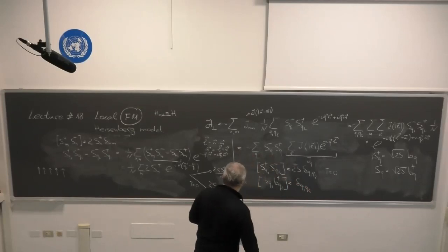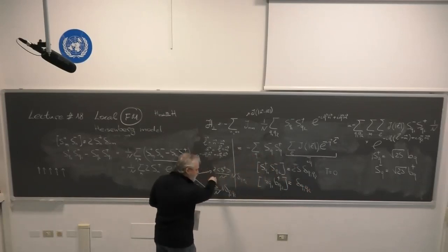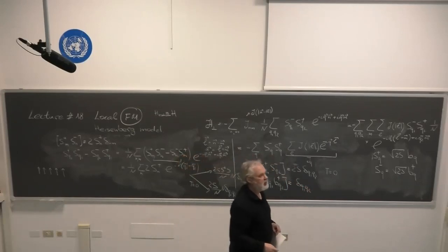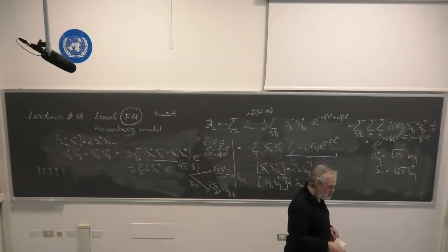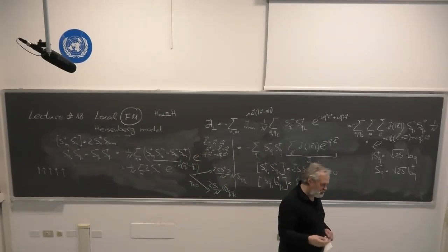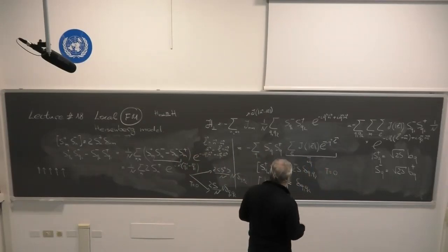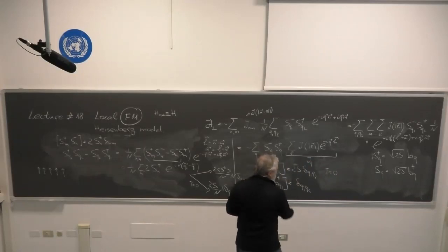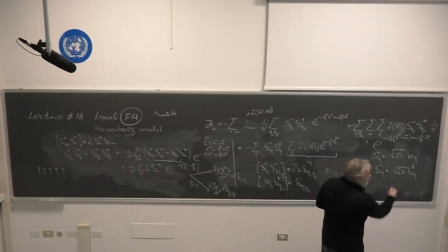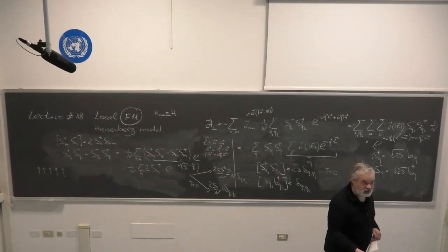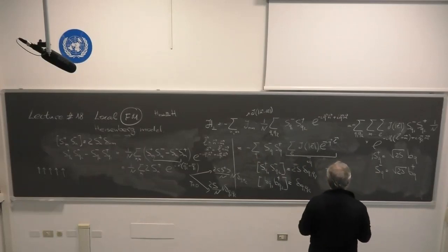So you see there is an approximation because I replaced the commutator with its value at the ground state or some average mean field value. However, apart from that, my transverse component behaves like a harmonic oscillator. So I already have a term which is proportional to b_q dagger b_q.